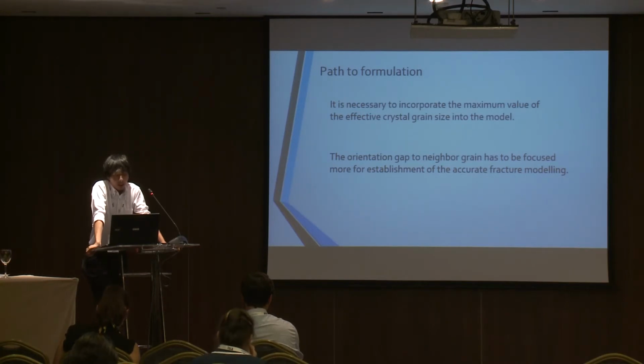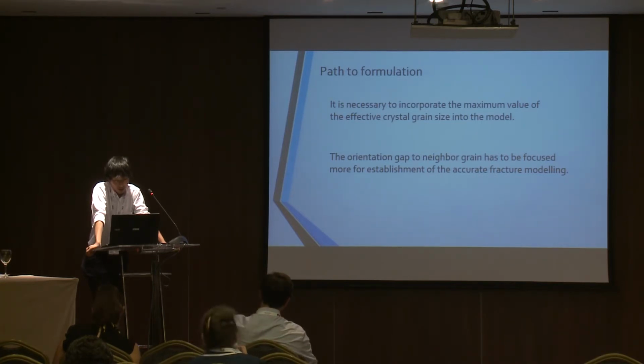From these, we show the path to formulation. First, it's necessary to incorporate the maximum value of the effective crystal grain size into the model, and the orientation gap to the neighboring grain has to be focused on more for the establishment of accurate fracture modeling.